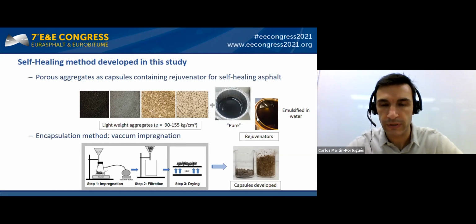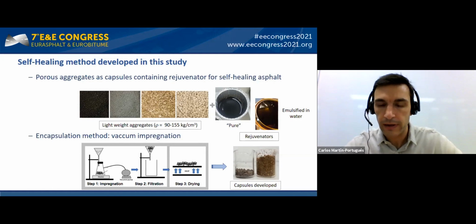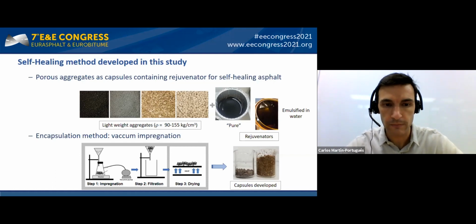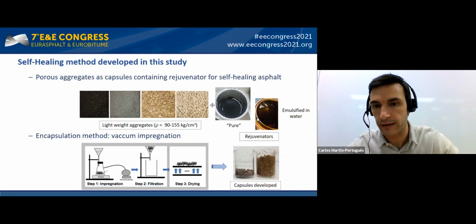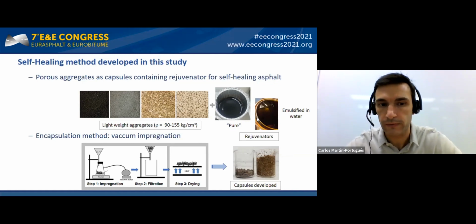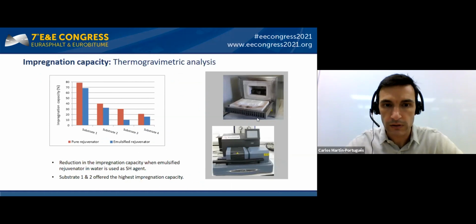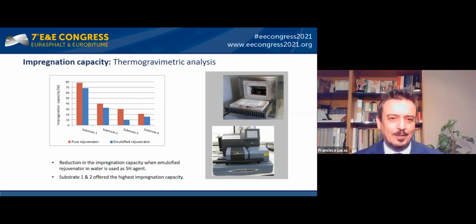So what we have developed is a new method for impregnation of porous substrates with pure and emulsified rejuvenators. Okay, the process is quite simple. It's about the impregnation, filtration, and drying to produce additives and capsules that can be suitable for blending with normal asphalt concrete. So with this technology, our colleagues from Repsol will explain about the impregnation capacity of this material. So Francisco, please go ahead. Thank you, Carlos, and good afternoon.